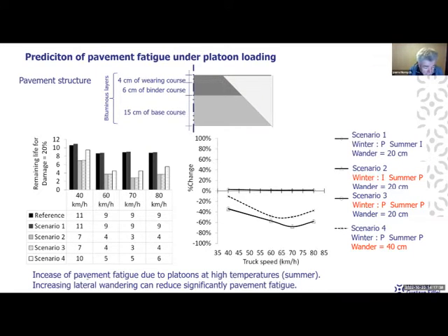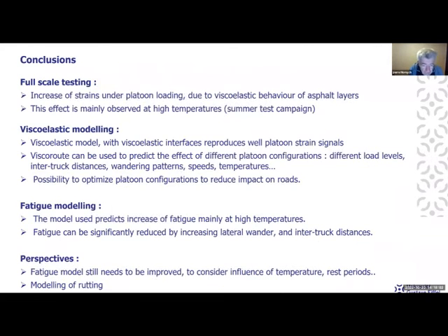So the conclusion is that the increase of pavement fatigue due to platoons is observed mainly at high temperatures, where you have these strain accumulation effects. Otherwise, the strains are the same as under an individual truck, and so there is no difference in fatigue. And by increasing the lateral wandering, you can significantly reduce this fatigue phenomenon. We also did other simulations for other conditions, but it's just to give you an idea of the type of work that we did.